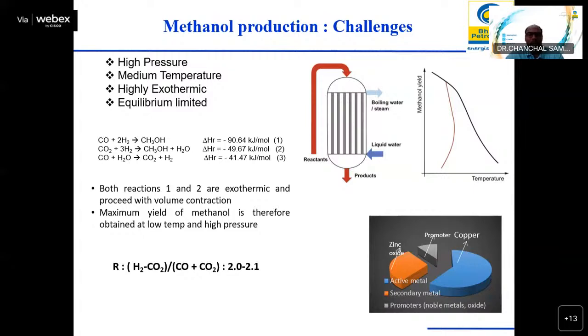And also we need to have a particular hydrogen to CO2 ratio. This is called the R factor, in the range of 2 to 2.1. A typical SMR process produces a very high amount of hydrogen, while coal gasification typically produces a hydrogen to CO ratio in the range of 0.7 to 0.9. So coal gasification also needs to be coupled with a water gas shift reactor to enrich hydrogen so that we can get the stoichiometric hydrogen to CO ratio of 2.